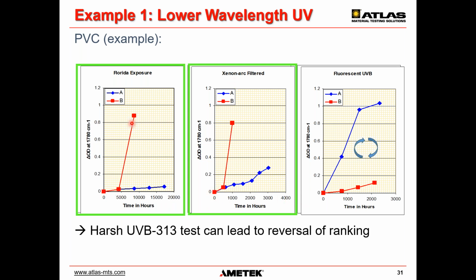This is an accelerated test, but the weathering behavior of this PVC is very similar between materials A and B. And now look at the data from fluorescent UVB. What you see is there's a reversal in ranking when exposing the material to UVB, fluorescent UV. In short, do different tests in daylight, get a different result.